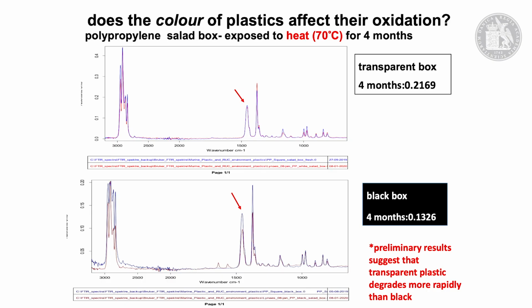Another basic question is, what about the colour of plastics? Well, at the moment we're just looking at transparent or white and black. But in the early indications, we can calculate something called the oxidation index or degradation index. The larger the number, the more degraded the material. And our initial results suggest that transparent materials are much more sensitive to degradation than darker materials or coloured materials.